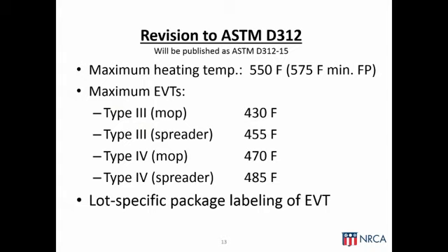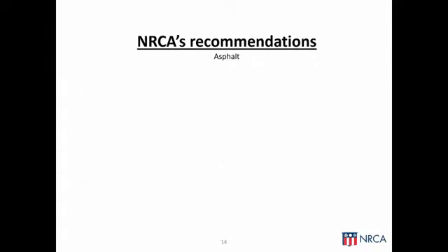And then finally, we want to get back to where the industry was probably about 20 or 30 years ago and get away from pre-printed package labeling that says something to the effect that the EVT of an asphalt is within a range of temperature. What the new standard is calling for is actually lot-specific package labeling of asphalt EVT. And like I said, this is the new standard, just published or just finalized last Wednesday, and published as of the 2015 edition of the ASTM standard.